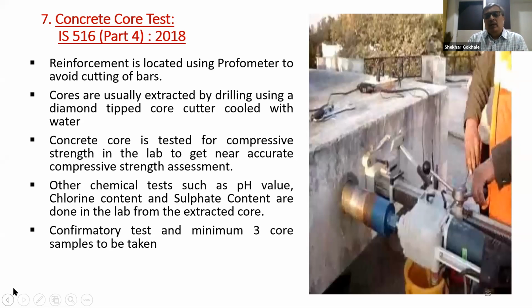And normally we suggest we should take a minimum of 3 samples. Even if a very small building is there, we should take 3-4 samples so that we can average out the equivalent cube strength. If the extent of the building is more, then we can definitely have more core tests. So the core test gives a fairly good idea about the concrete strength of the building.